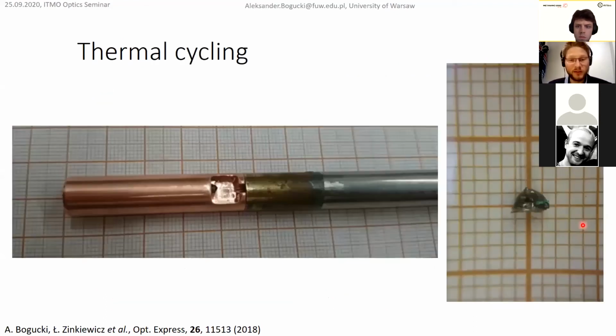And we tested it at low temperatures because we are interested in the semiconductor business, right? So this is an example of an optical fiber glued with ultraviolet resin to our sample, and this is the droplet of glue on top of it. This glue was again a photosensitive glue, so the procedure was like that.